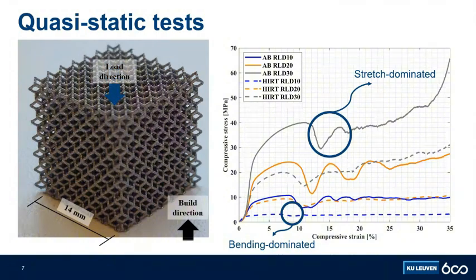For the quasi-static compression tests, I have applied a compressive load in the -z direction, opposite to the build direction. And what we can see here from the diagram, the dashed lines are the hardization treated, and the solid lines are the as-built as manufactured. So we can see a gradual transition from a bending-dominated behavior to a stretch-dominated behavior with increasing relative lattice density, which is consistent with other researchers' work as well.